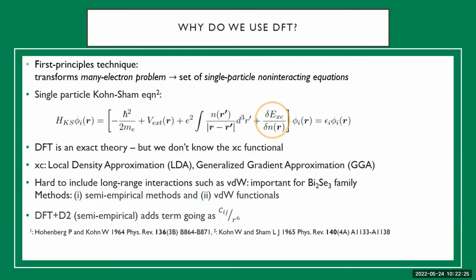And they end up working quite well for a lot of materials. However, it is hard to include longer range interactions, such as the van der Waals interaction, which is known to be important for the bismuth selenide family of materials. Van der Waals interactions basically arise from dynamic polarization of electron densities of atoms, and they lead to the formation of instantaneous dipoles in these materials. And the dipole-dipole interaction goes as 1/r⁶, as we studied in E&M quite a while ago.